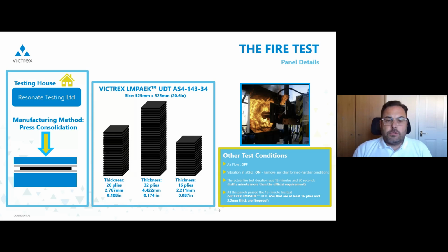The material that we used is the Victrex LMPAEK UD tape, that's made with AS4 fiber. The 143 that you see there is the GSM, the FAW, fiber areal weight, and 34 is the nominal resin content.